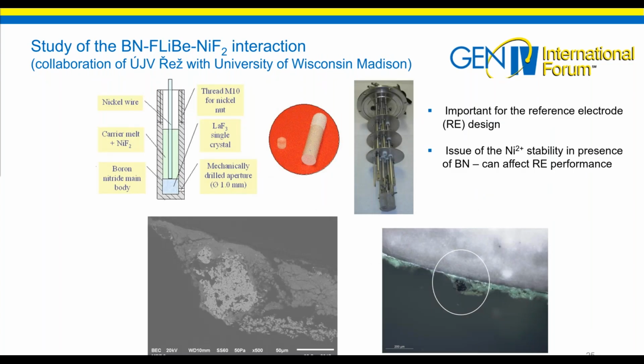here is information about our development of a reference electrode, because there is no standard reference electrode for electrochemical measurement in fluoride media. This is the difference if we compare it with chloride media. And therefore, we had to propose our own design of the reference electrode based on the electrochemical couple nickel 0, nickel 2 plus.